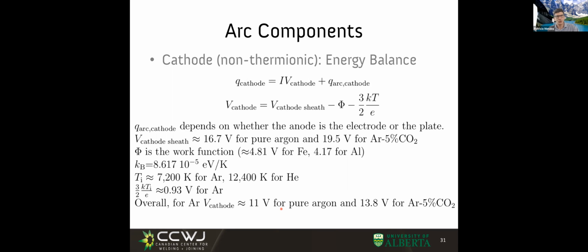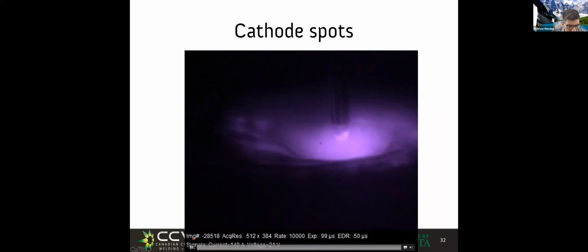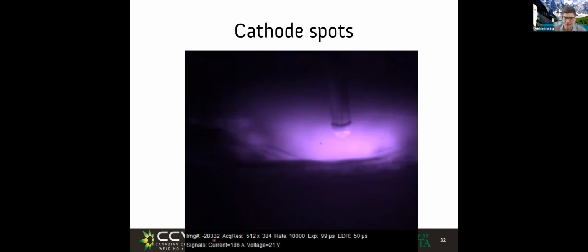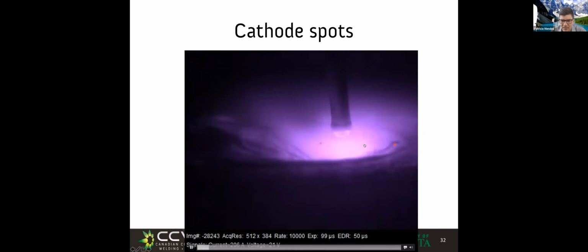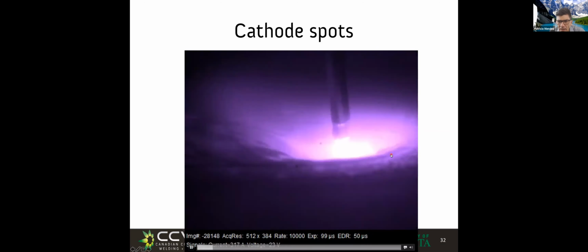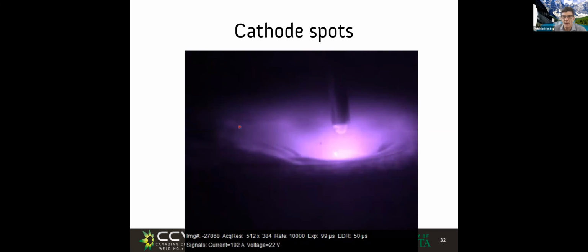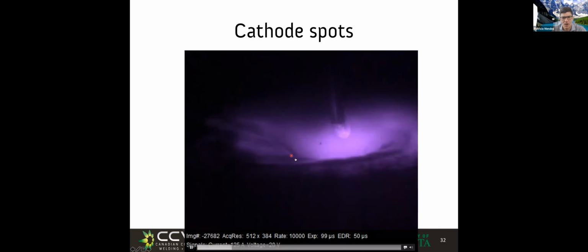And because the energy is current times voltage, and the voltage is more or less constant, you get to see immediately how the amount of energy you put in is proportional to the current. I have a video here. If you see this video, this is MIG welding of aluminum, and you're going to see some kind of a shimmer, right? This is 10,000 frames per second. The cathode spots, the little mini lightnings, happen in millionths of a second. So we're not seeing the lightnings properly, but you see a shimmer.